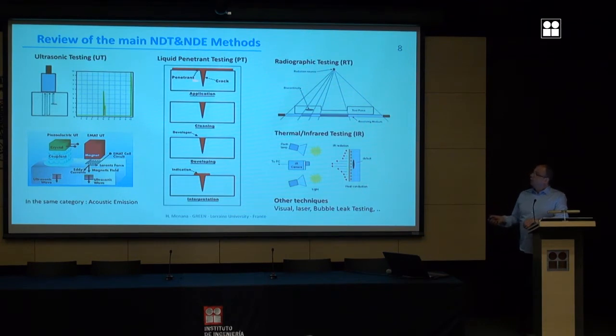In this method, we begin by cleaning the tested piece, and then we spread on it a particular liquid. We wait a certain period until the liquid penetrates the flaws, the cracks, by capillarity effect. We clean the material again, and then we spread a developer on it. The developer will absorb the liquid that penetrates the cracks, and then we have a map of the cracks on the surface of the tested material.